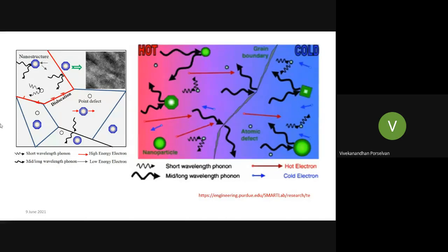Okay. So here in the first figure, just look at the nanostructured material. We have different kinds of things. We have the point defects like porosities, and we have the grain boundaries, which separate two different grains that are oriented in different directions, and we have the doping stuff. So doping is a point defect, or a point chemical defect, that we can say. So here whenever the short wavelength and mid wavelength phonons are coming forward, moving from one state to another, normally from a higher energy state to a lower energy state, what will happen? Some kind of transportation will occur. It will move with a higher momentum. So as it moves here, it will interact with the different kinds of defects that are available in the bulk material.